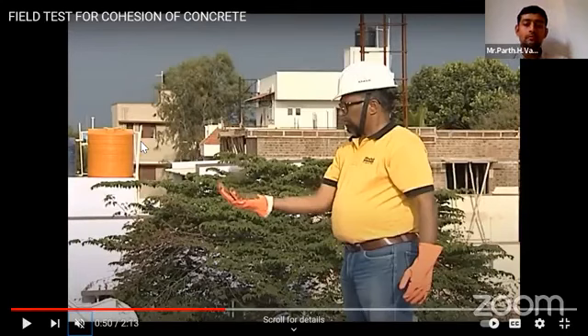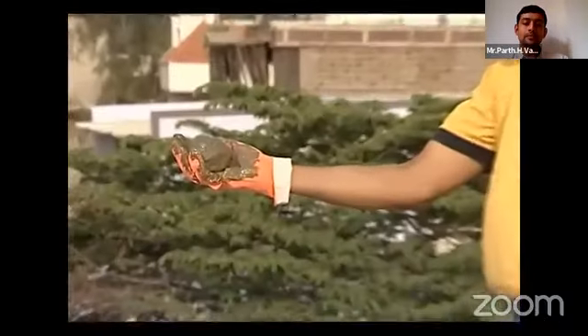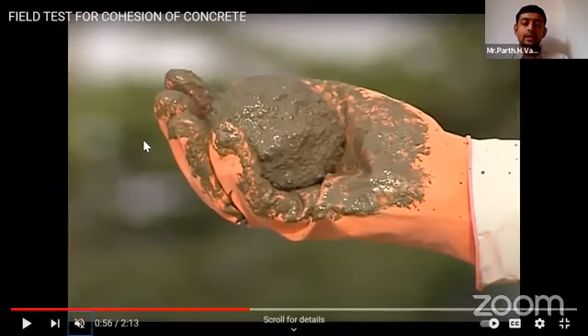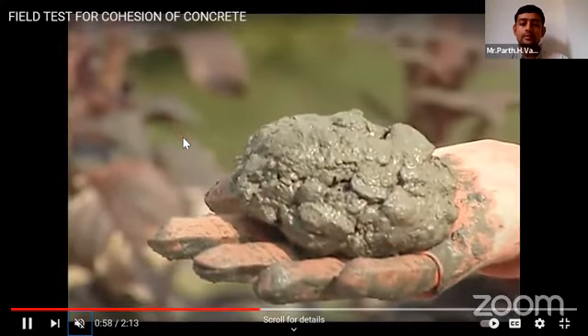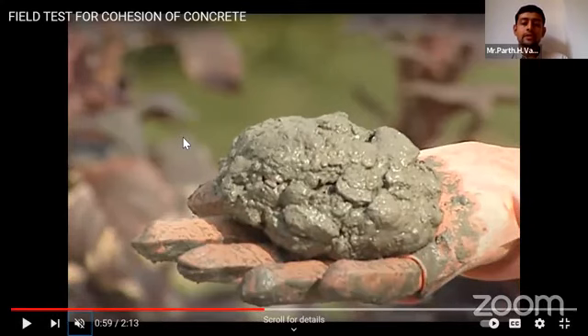If we cannot make a ball from the fresh concrete, that is the problem. After that, we should take the ball in hand and throw it up to 6 to 8 inches of height, and it should stay as it is, as shown in the video. If any crack appears, or segregation, or any core segregate comes out from the ball, then the concrete mix is not proper, meaning the concrete is not cohesive. This shows that if the concrete is not proper, then this type of cracks and core segregate can come out. So the ball shown is not a proper cohesive concrete.